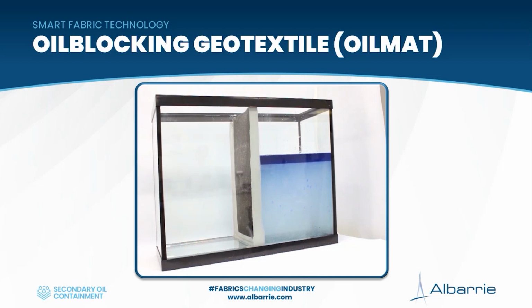So let's imagine, for instance, that you have a containment system using this material installed. Say that there is an event where it's raining and you also have a catastrophic equipment failure at the same time. Both things are going to fill into the containment. You're going to have a mixture of oil and water. The higher concentration of oil is going to rise to the top of the water. The water is going to continue evacuating the containment system through the floor. Small trace amounts of oil will be removed and captured within the mat itself, so that liquid passing through that floor and coming out on the other side is clean and meets the minimum discharge requirements set out in North America.